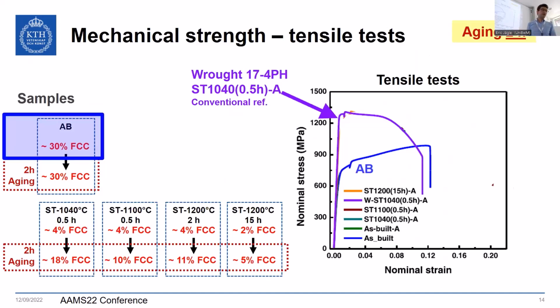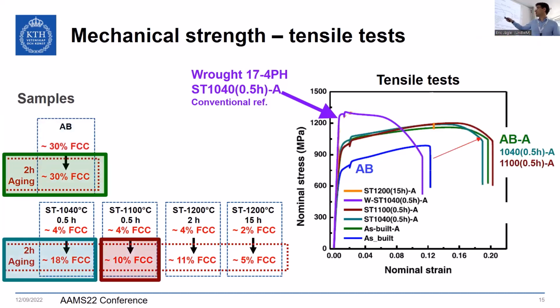Okay, so now I'm going to finally present the mechanical properties in terms of tensile strengths. We compare those data to a wrought 17-4 PH, which is your conventional process reference. It's in yellow, purple. And in the as-built state, we see that it's much below in terms of yield strength and so on. But if we apply this aging, then we increase the yield strength, and also the elongation to rupture, or the ductility.